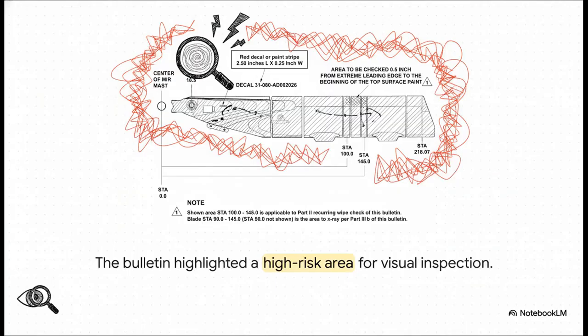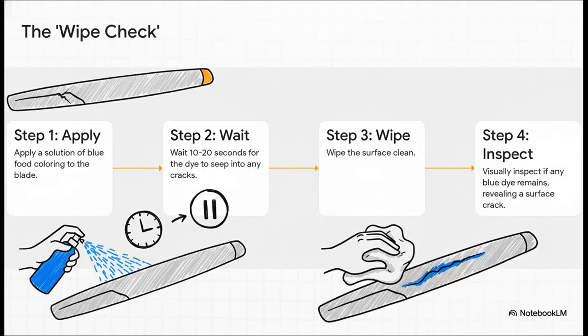The bulletin basically zeroed in on this one specific section of the blade, telling everyone this was the high-risk area. The whole idea was to have mechanics visually inspect the surface of the blade in this zone, hoping they could catch the fatigue crack, if and when it finally broke through from the inside. And the procedure they came up with? Well, it was surprisingly low-tech. They called it the wipe check.